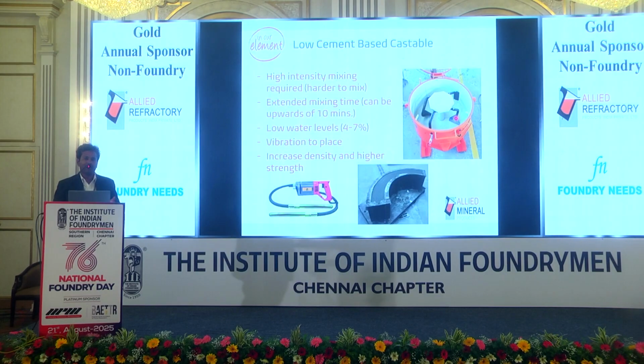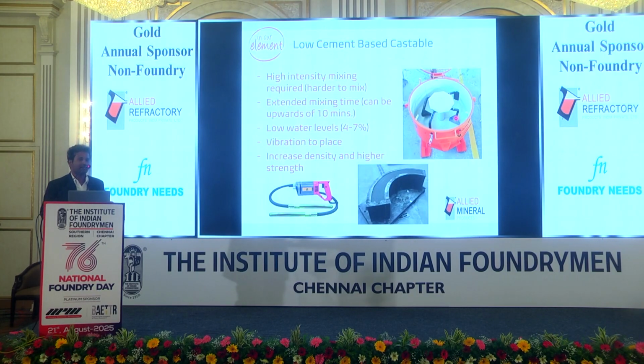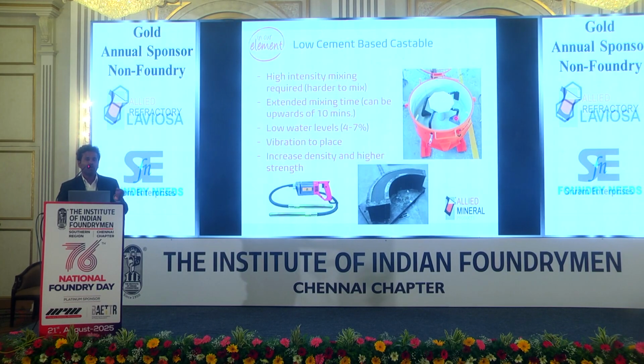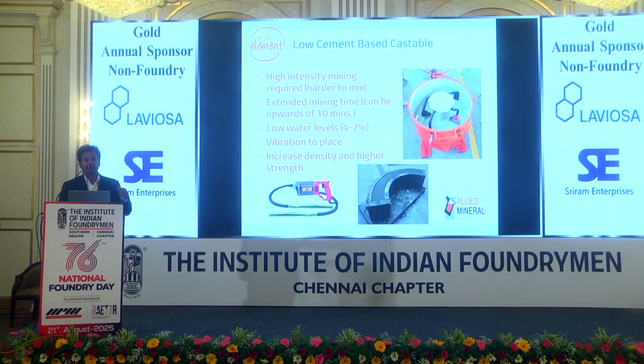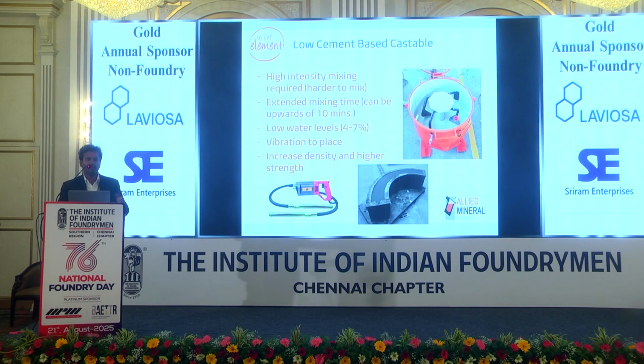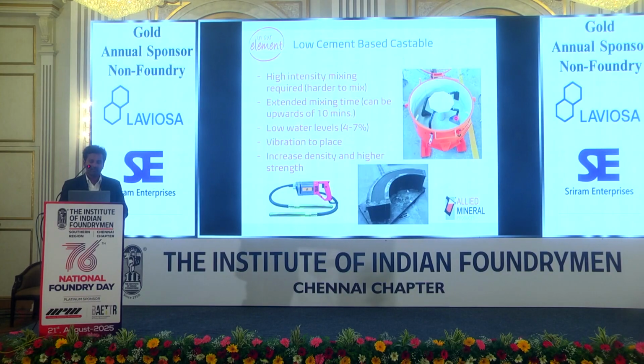It cannot be mixed by hand. When you try to mix a low cement castable by hand, you tend to add more water, which ultimately reduces the density of the product. Ultimately, it reduces the strength and results in lesser lining life.